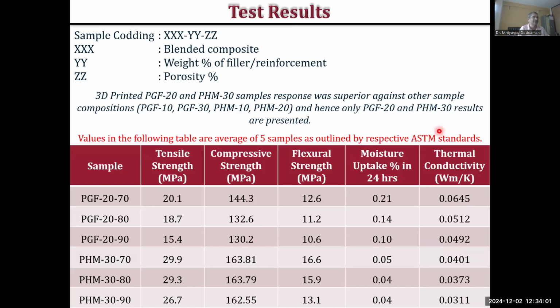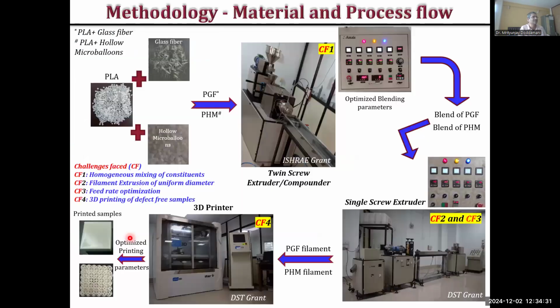Then we printed this Kelvin structure and then went ahead with, as per ASTM standard, the experimental evaluation of the thermal conductivities. And you can see all the values here. So this is again glass fiber, hollow microballoon, no doubt with the other additive. So 20 is 20 percent by weight of glass fibers and 70 is the porosity level. So this 20 number decides how much content of glass fiber or microballoon you are adding in the base material. Here we went ahead with 30, and then the porosity level is being changed from 70 to 80 to 90. And what does this porosity level change?